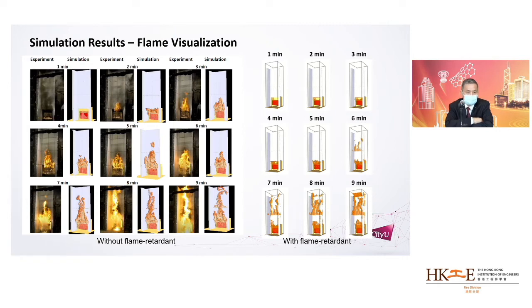slide. You can clearly see that the photos depict the development of the fire over the burning facade from 1 minute to 9 minutes. And along with it, there are CFD calculated predictions that compare extremely well, even down to the spread between panels. If you look at the slide very carefully, you can see that there is a lower panel and an upper panel. And the flame in the experiment spread around 6 minutes from the lower to the upper panel for this facade without flame retardant.